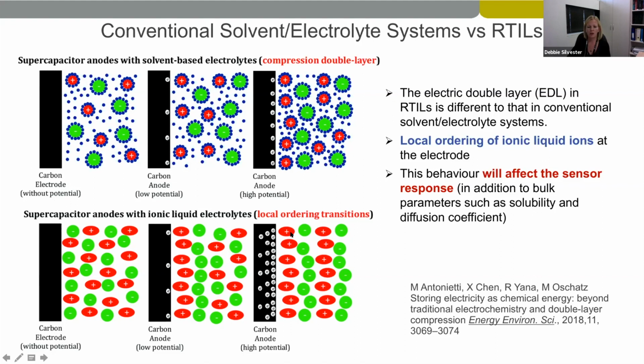And there's been a lot of work about this done, especially by Kornyshev, to look at the electrical double layer in ionic liquids. And people like Rob Atkin at UWA have looked in detail at how the layers build up at the electrode surface. But generally, it's believed that if you have a negatively charged electrode, you have positively charged cations on the surface, and then you have alternating layers of anions, cations, anions. And so this different structure at the electrode will also affect the sensor response.